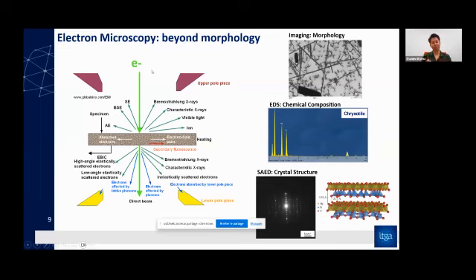Because when we pass an electron through a sample, there are many interactions going on. And this is what we want. Depending on the chemical nature of the sample, we might have a characteristic X-ray emission, which we are able to see using energy dispersive spectroscopy. So for example, chrysotile contains magnesium and silicon, amosite has iron content, or tremolite has calcium. So that allows us to differentiate between these different structures. Similarly, in transmission electron microscopy we are able to see the crystalline nature of the fibers we are trying to analyze. Therefore, electron microscopy gives us information beyond just the morphology.